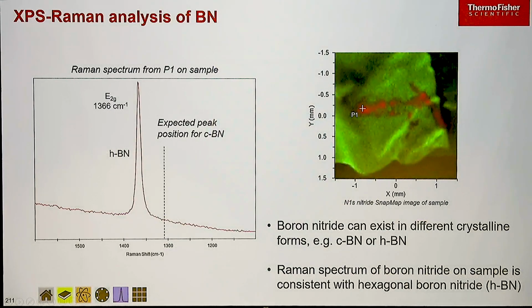And then we can do Raman spectroscopy at the same point as well. If it was cubic boron nitride, so if it wasn't the 2D form, we'd see a peak here at just above 1300 wave numbers, but we see the peak here at 1366, which is characteristic of hexagonal boron nitride. So we are at least getting a very small amount of the right material, and it's just a question now of refining the synthesis process to make sure that it now covers the surface.